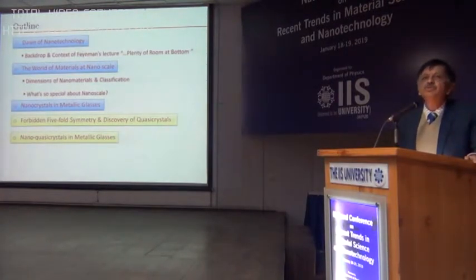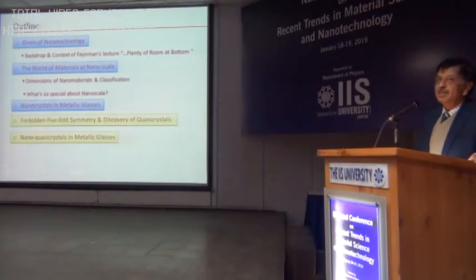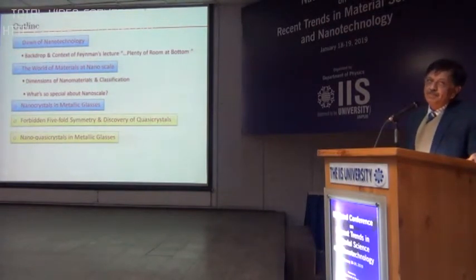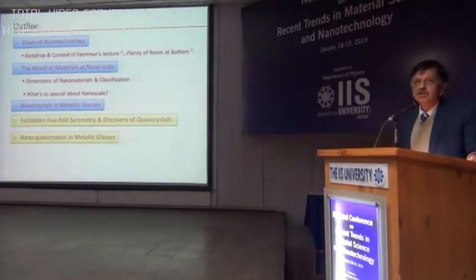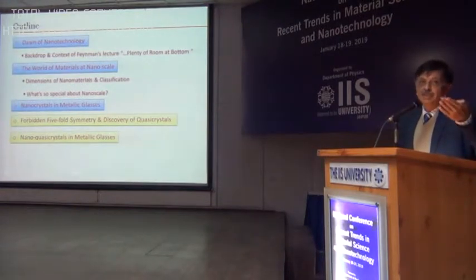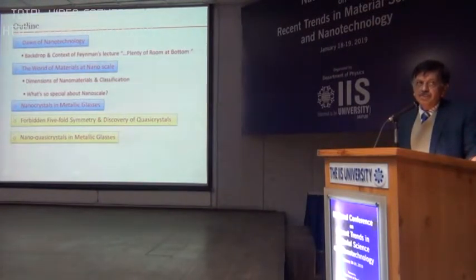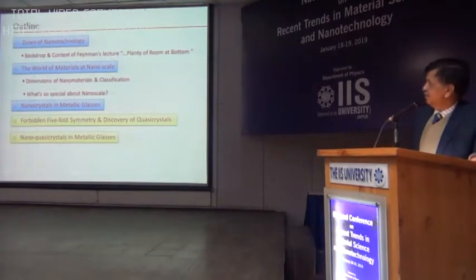They are metallic systems, so you have to do controlled annealing, and you take it up to that target temperature. Of course, you decide the temperature strategically, and then by choosing that temperature, you put it inside the furnace for a fixed amount of time, 5 minutes, 10 minutes, and then you observe the crystals, mostly in transmission electron microscope or XRD if the sample is bigger in size. Most of the samples which I will be talking about will not be bigger in size, so it is transmission electron microscope study which will be presented, so that you have a feel of how to get this nanocrystalline phase. Next one.